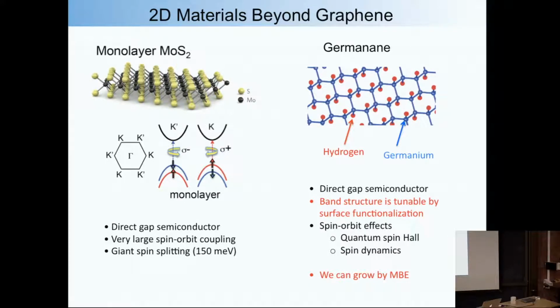But, yeah. So the transport is tricky because it's a semiconductor and it's very thin, so the resistance is very high. And when we put down contacts to it, there's Schottky barriers. So our first sort of completed work in MoS2 was to study Schottky barrier formation. And it's really confusing because normally you think about a Schottky barrier, you put things down and they form a Schottky barrier into the material. But in this case, into the material is 1 or 3 atomic layers. It's like very thin. So the thought is that the Schottky barrier happens, but it's going laterally, maybe.